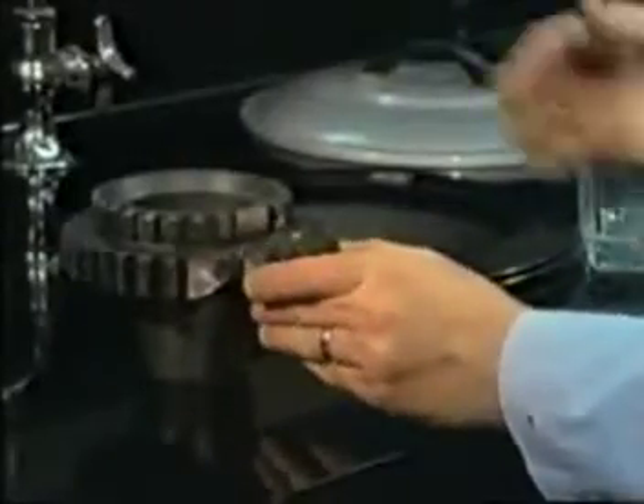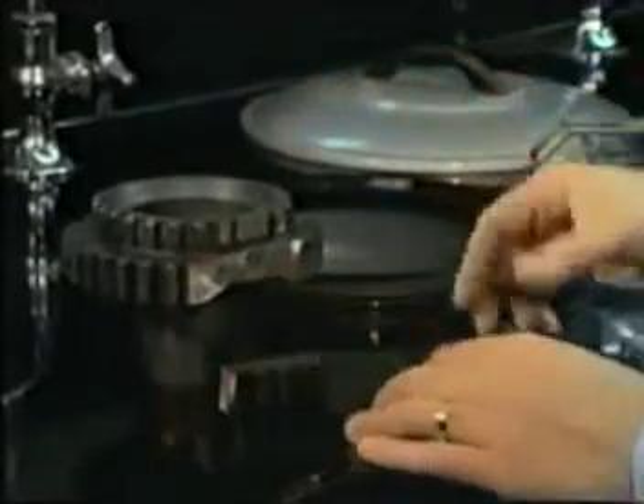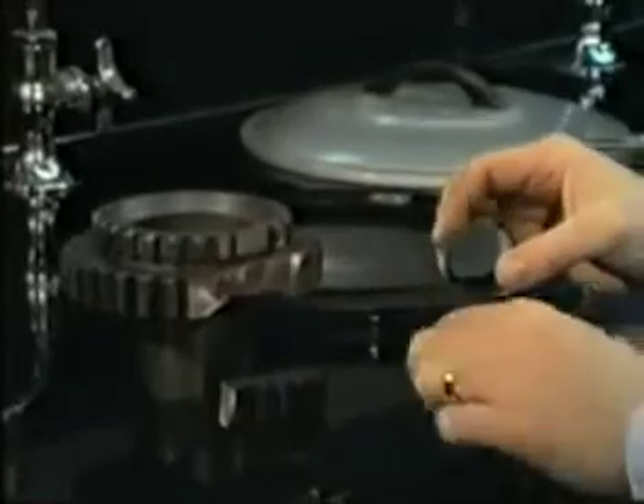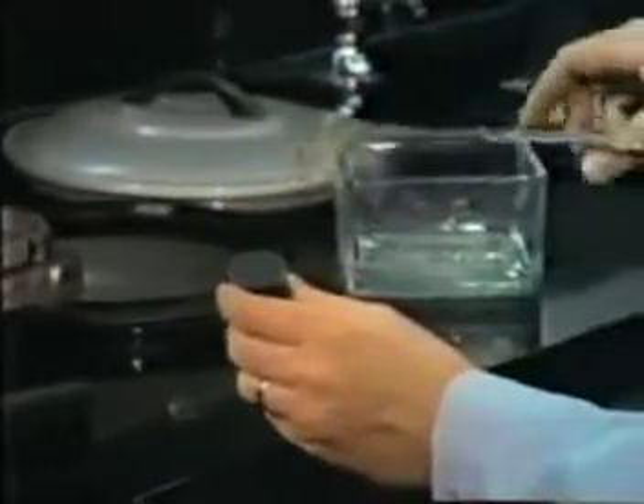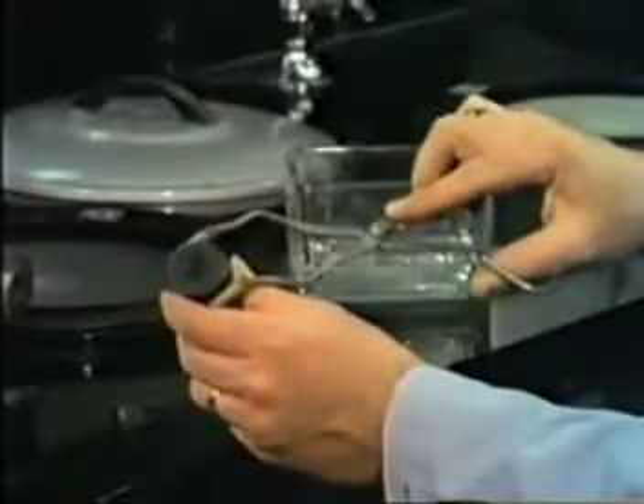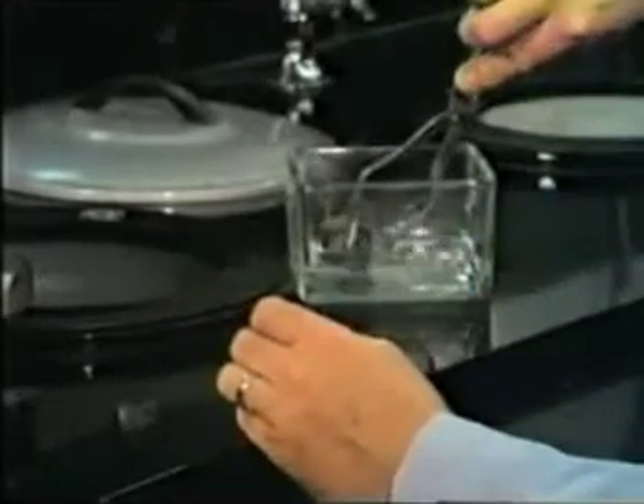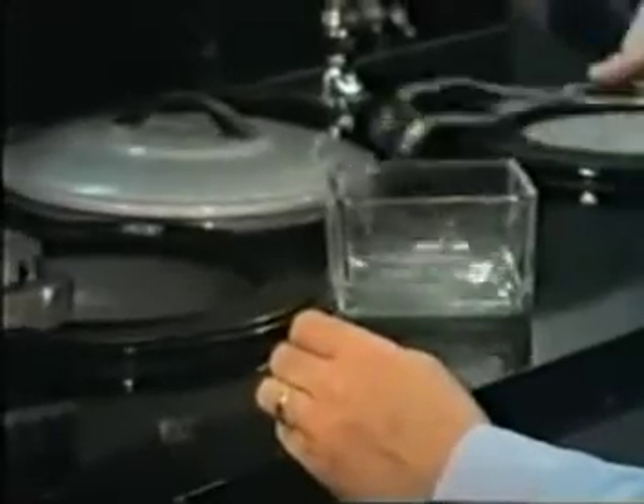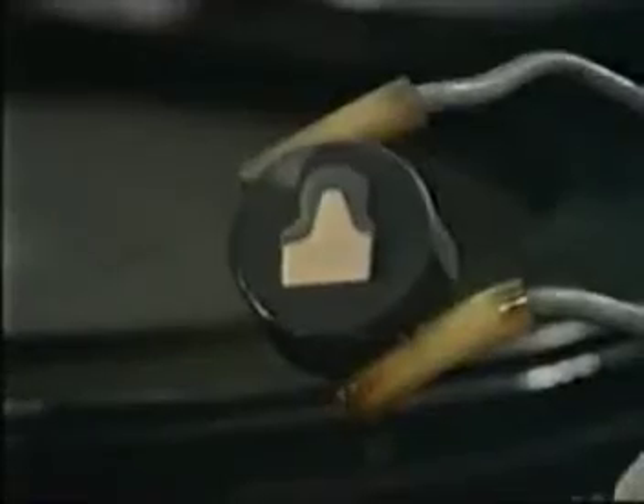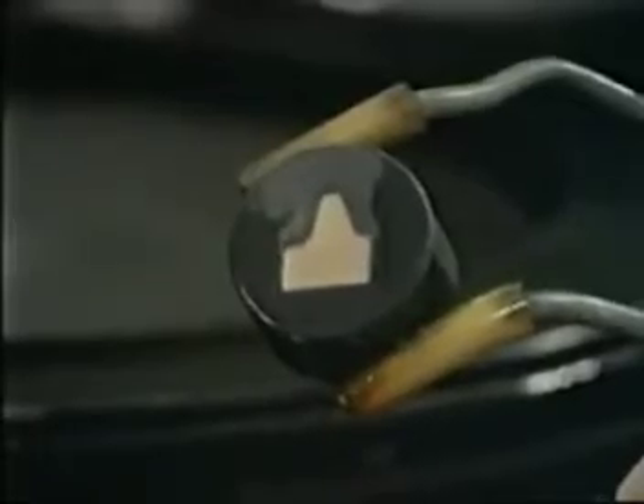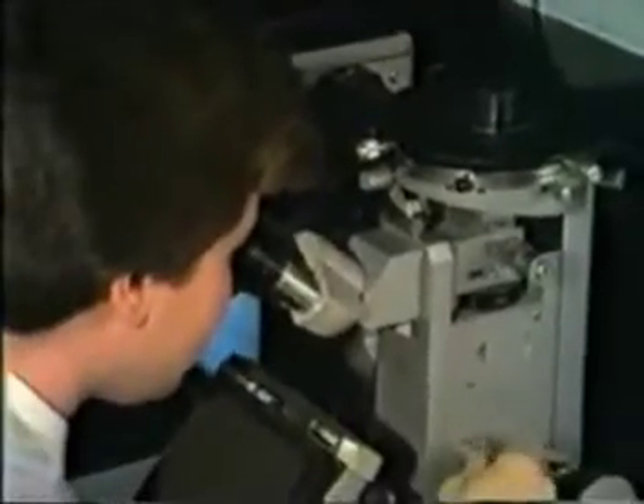A common method used to check case depth and steel structure quality is to cut a representative cross-section from a part. This specimen is then polished to a mirror-like finish on the surface to be inspected, followed by etching in a suitable solution to bring out the cased area. The sample is then measured with a Brinell glass, or if a more accurate measurement is required, it can be examined under a microscope. Oftentimes, a magnifying television-like screen is used to make viewing easier.